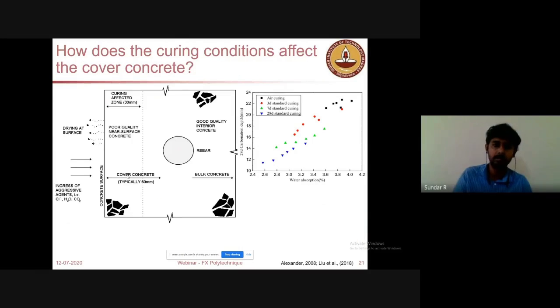But when you have inadequate curing, for example, when you are at site dealing with PPC or PSC, and you don't cure your concrete properly, you could have a curing affected zone of up to 20 mm. It has been identified as mostly affected by curing, when there is drying happening. If it is not sufficiently cured, this concrete will not achieve the necessary durability properties, like the much denser concrete here.